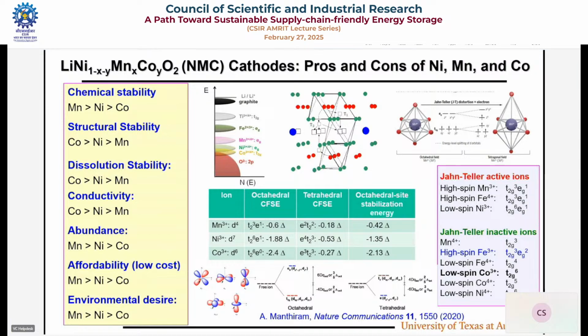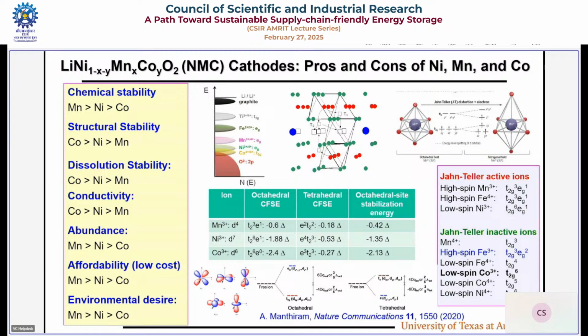You see here iron, I told very early. Oh, iron doesn't work in layered oxide, give up and keep going. Nobody ever explained why it is. You see here, iron is high spin, 3 electrons here, 2 electrons here. Crystal field stabilization in the octahedral site, stabilization energy will be 0. If it is 0, iron 3+ has equal stability in the tetrahedral site and octahedral site. Very easily moving from that to here, worse than manganese 3+. So that's why we do not have any iron containing layered oxide. In the case of sodium, sodium is big, it doesn't want to form spinel, so we are able to use iron in the layered oxide for sodium ion batteries. So we can understand all those. There are few other criteria, you can also see that here.